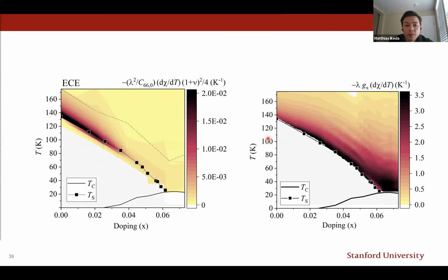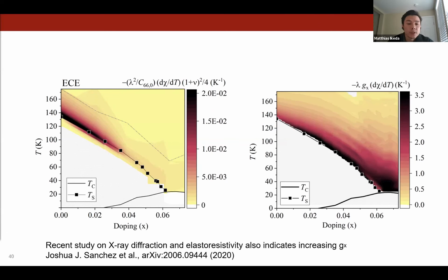But at the same time, the coupling of the charge carriers and the nematic degrees of freedom increases by an order of magnitude. And let me point out here at the end that this result is also perfectly in line with a recent study on X-ray diffraction and elastoresistivity put forward by Joshua Sanchez and others from Jim Analytis's group very recently.